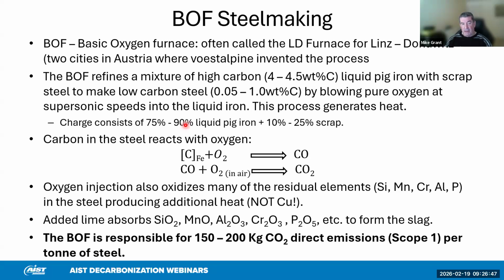The charge typically consists of between 75 and 90% liquid pig iron and 10 to 25% scrap. The primary reactions that take place: the carbon in the hot metal from the blast furnace is burned with supersonic oxygen. It makes CO. And then that CO is burned as a fuel with oxygen, primarily in air, to produce CO2. And this is where the emissions come from. We get energy from this reaction with carbon, and we also burn out some residual elements such as silicon, manganese, chromium, aluminum, and phosphorus. The combustion of these produces oxides, which are removed in the slag, and this combustion process gives energy to the process. So in total, BOF is responsible for between 150 and 200 kilograms of direct CO2 emissions, or scope 1 emissions, per ton of steel.